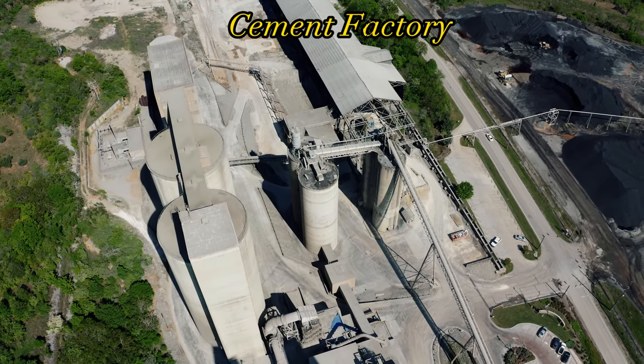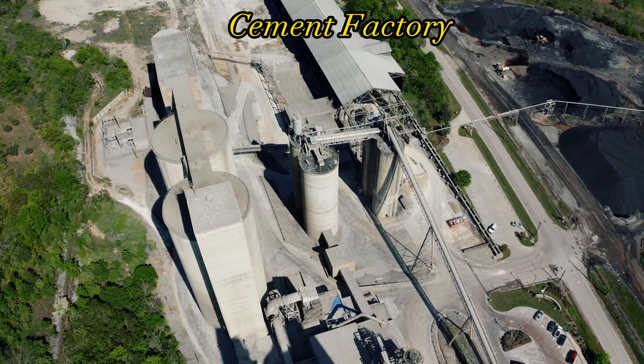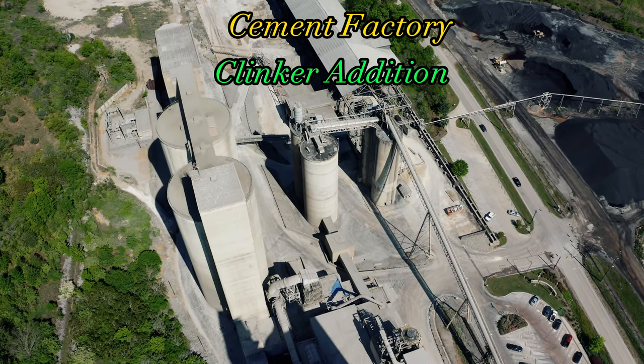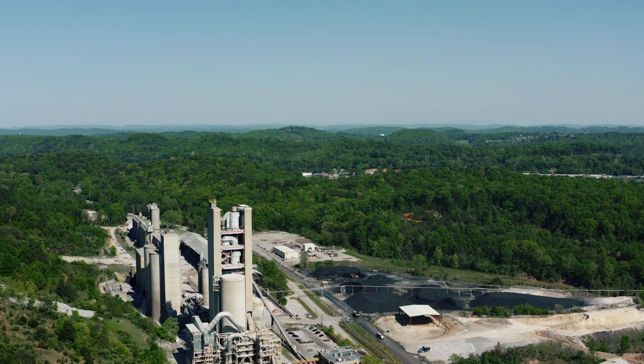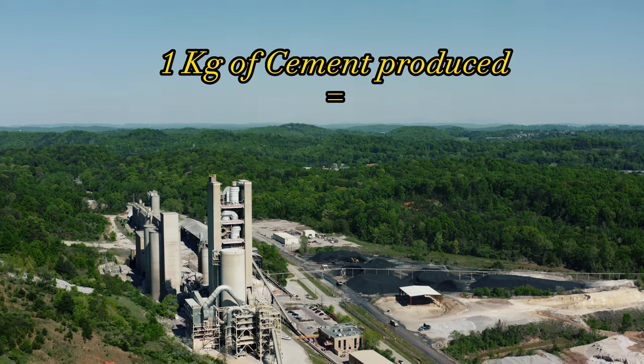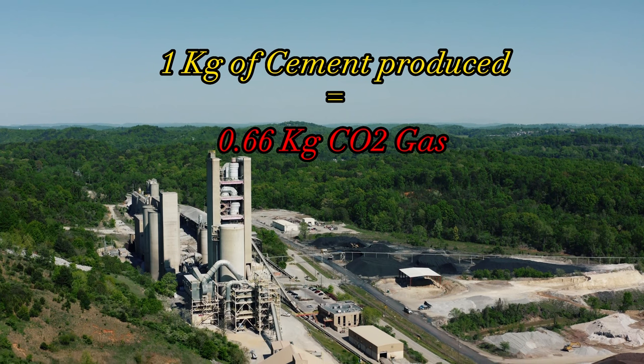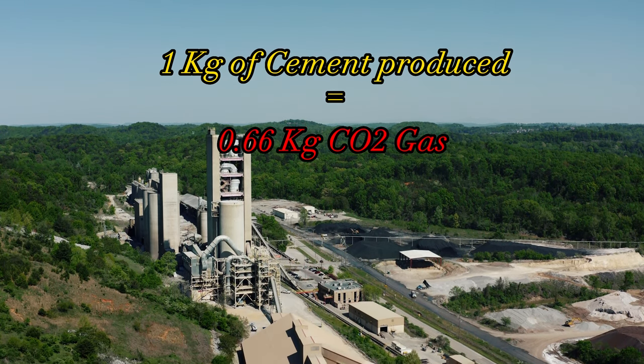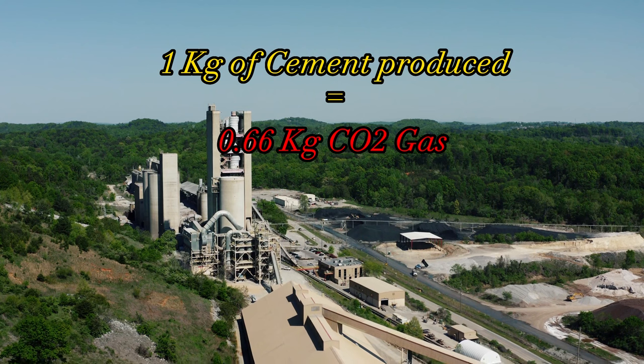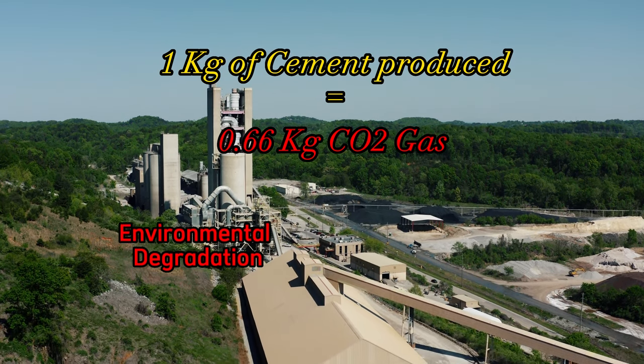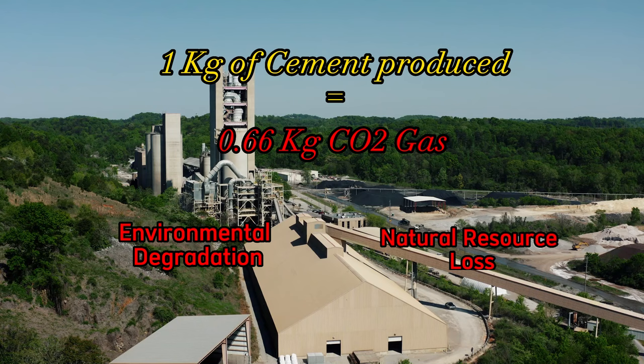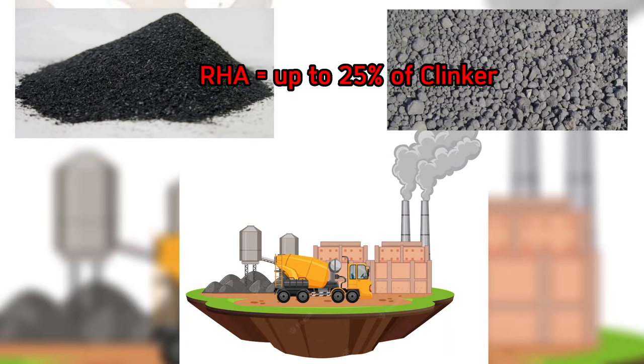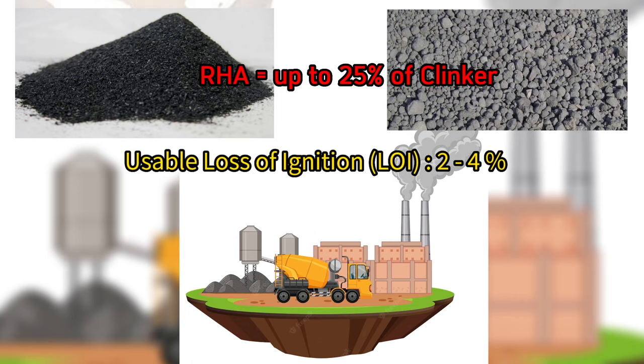Another way to introduce rice husk ash in cement manufacture is by using it as clinker substitution. Researchers have shown that for every 1 kilogram of cement, approximately 0.66 kilograms of carbon dioxide gas is released into the atmosphere. The increasing demand of cement leads to higher rate of environmental degradation and more exploitation of natural resources for raw material. On average, it has been shown that rice husk ash as clinker substitute can be up to 25%, and the loss of ignition of husk ash used can be from 2 to 4%.